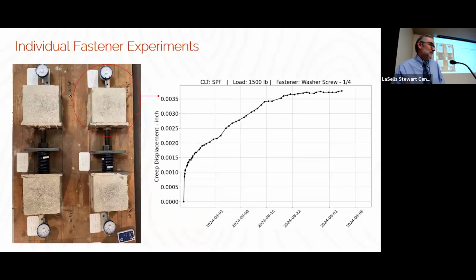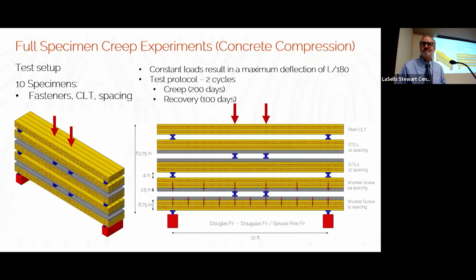And here's an example of that creep behavior. This is 40 days of creep behavior, not showing you the initial elastic deformation. So it's clearly a nonlinear performance. In that first hour, you get a lot of the creep, and then slowly it starts to taper out, but they're still moving. We've got about a 50% change in stiffness compared to the elastic stiffness in 40 days. It's not small, even though the actual measurements are fairly small.